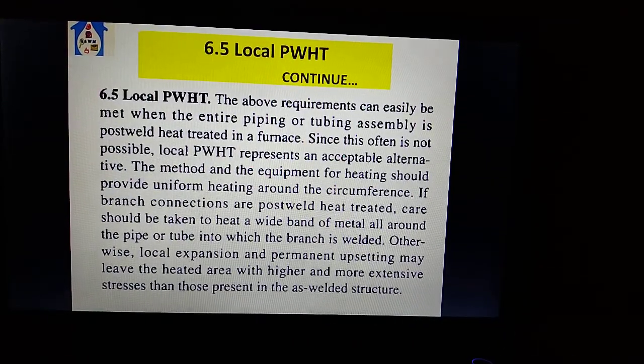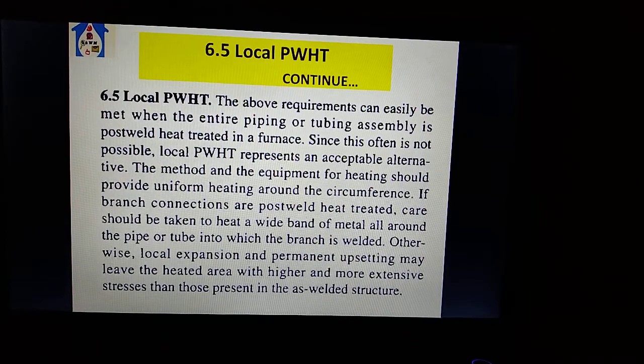Local PWHT. The above requirements can easily be met when the entire pipe or tubing assembly is postweld heat treated in a furnace. Since this often is not possible, local PWHT represents an acceptable alternative. The method and the equipment for heating should provide uniform heating around the circumference. If branch connections are postweld heat treated, care should be taken to heat a wide band of metal around the pipe or tube into which the branch is welded.